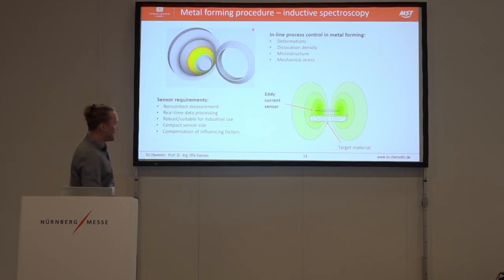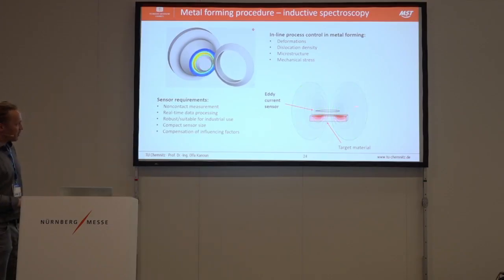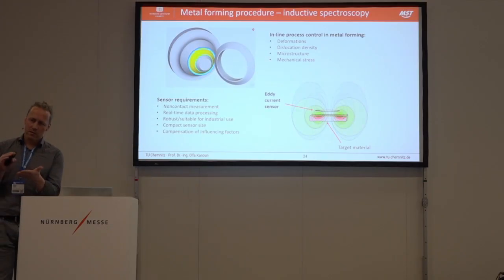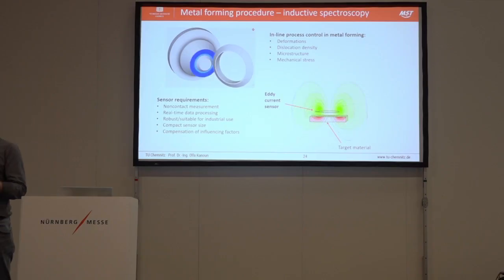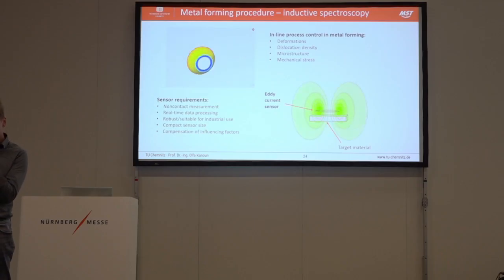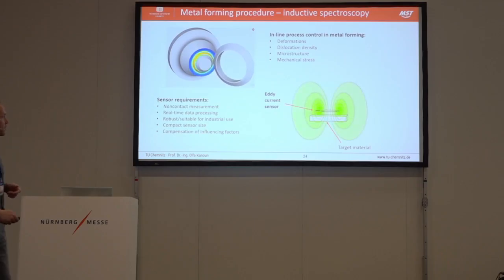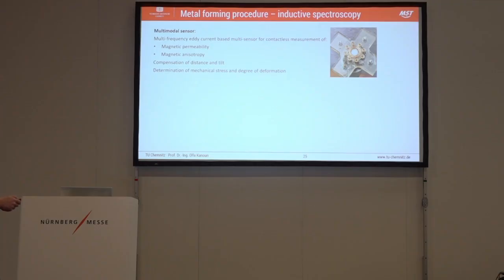Here, quickly, the eddy current. We have a coil. In this coil, we also put our multispectral information. And here, the relevant phenomenon is the so-called skin effect. If you have a high frequency, the eddy current is scratching on the top. If you have a low frequency, the eddy current is going deep into the material. And so we can take a look inside the material without destroying it. So this is our current approach.